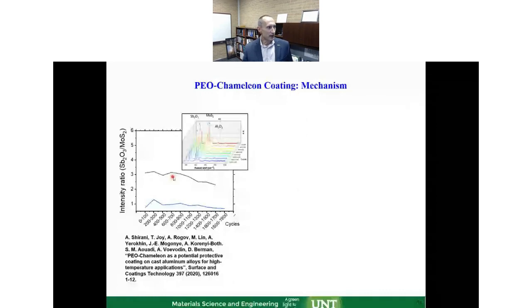So to quantify it, we plotted the ratio of antimony trioxide to molybdenum disulfide, and we see that it's going down. These are two different tests, just to show that it goes down during the test. So we have less antimony trioxide presence and more molybdenum disulfide presence on the surface. So what's going on in here?